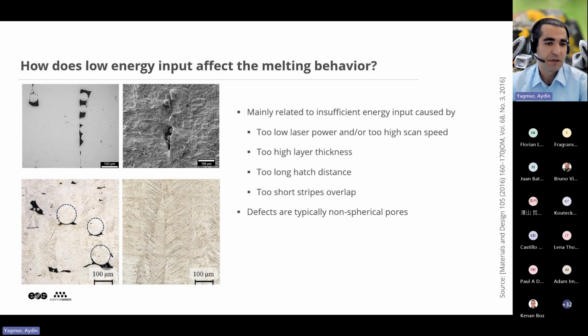You see different visuals here, an SEM picture on the top right side, and also metallographic pictures, and we can also estimate the shape of the metal powder, the raw material, which was not fully fused or melted. This is why we call it lack of fusion. So this is what happens if the energy input is less than the optimum values.